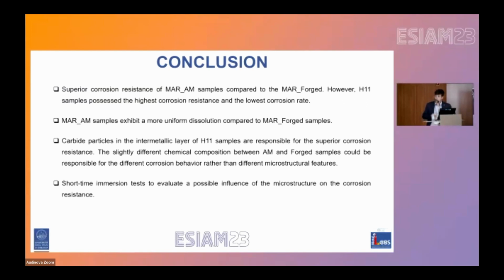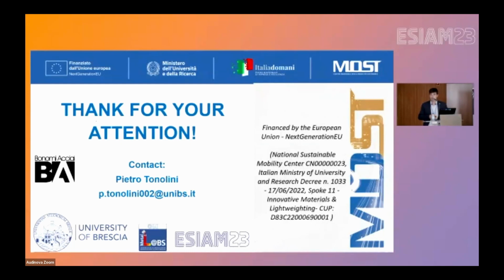However, due to the slightly different chemical composition between the tested maraging samples, it was not possible to understand whether or not there is a possible influence of the microstructure on the corrosion behavior of the sample. So short-time immersion tests are needed to evaluate the possible influence of the microstructure on the corrosion resistance of maraging steel AM samples. And thank you for your attention.